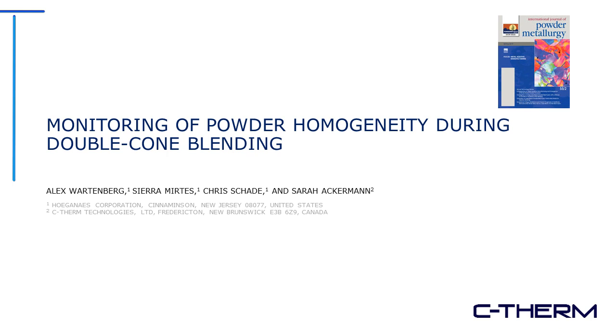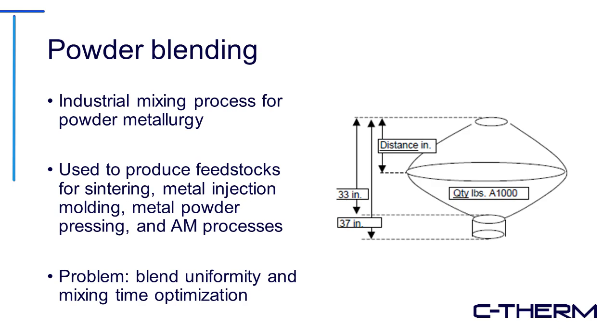So getting into a little bit of powder blending, it's a really common way to make powder mixes for metallurgy, both for metal injection molding, but also for additive manufacturing processes. And usually what you're going to do is have a blender that can blend, depending on the needs, between about half a ton up to several tons, or in some cases tens or hundreds of tons of the material. And the most common blender is this sort of blender here, which is kind of a double cone blender. You can see it's quite symmetrical in terms of its construction.